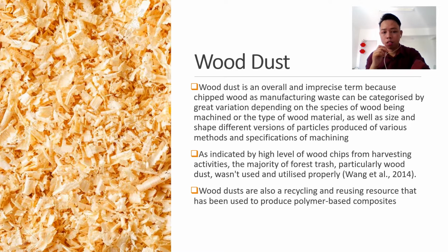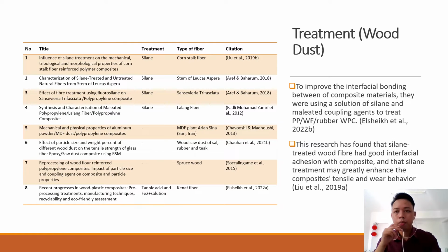Because it is degradable and able to be used. Treatment. This is the treatment for wood dust. The purpose of this treatment is to improve the interfacial adhesion between composite materials, using a solution of silane and also a coupling agent to treat the PP wood fiber or rubber wood plastic composite. Some research also shows that silane-treated wood fiber has good interfacial adhesion with the composite, and that silane treatment may enhance the composite's tensile properties and wear resistance.